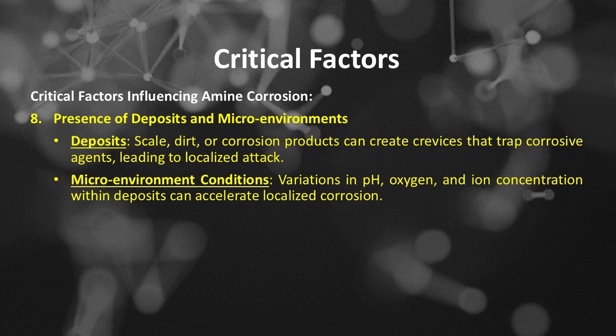Critical factors influencing amine corrosion. Number 8 is presence of deposits and microenvironments. The presence of deposits, scale, dirt, or corrosion products can create crevices that trap corrosive agents, leading to localized attack. The presence of microenvironment conditions: variations in pH, oxygen, and ion concentration within deposits can accelerate localized corrosion.